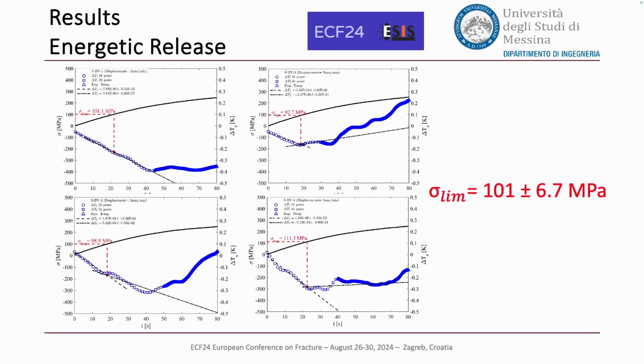And we can definitely say that the first phase is linear and decreasing, and the second phase has a variable slope between the different cases. The sigma limit, that is the sigma of first damage that we found, is about 100 megapascal. So we can say that the static thermographic method is really complex for composite materials, and because we have significant variability in the results, it requires particular attention from the operator.